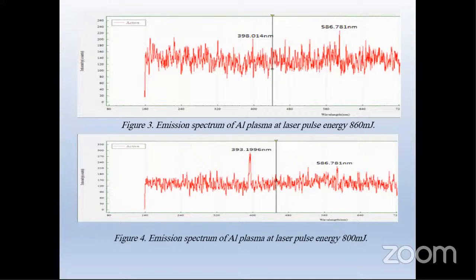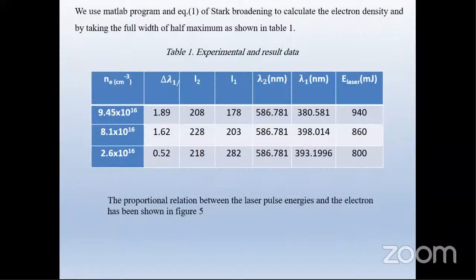Figure 3 shows the emission spectrum of aluminum plasma at laser pulse energy 860 millijoule, and figure 4 shows the emission spectrum of aluminum plasma at laser pulse energy 800 millijoule. We used a MATLAB program code and equation 1 of Stark broadening to calculate the electron density, by taking the full width at half maximum as shown in table 1. Table 1: experimental results and data.